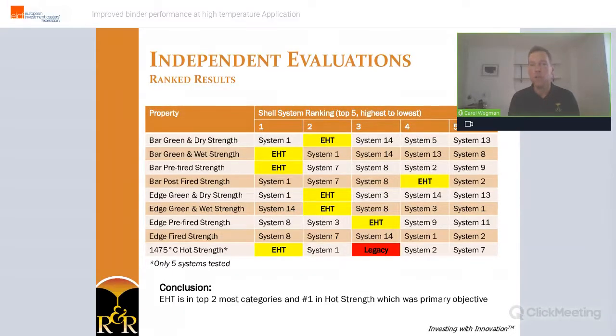This table shows the ranked results of the 16 systems that were tested at the university. And as explained, I don't have specific results, but based on this table, EHT jumped out in being the second best at dry green strength, best in wet green and pre-fired strength, best in high temperature for hot strength. It was low on post-fired strength,